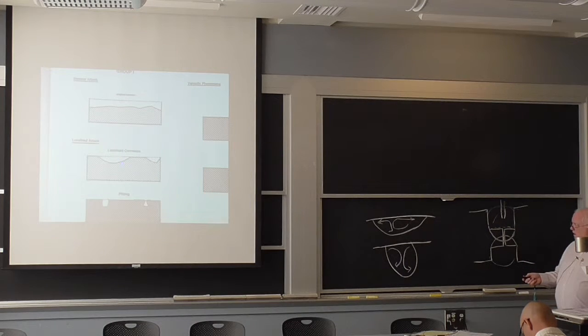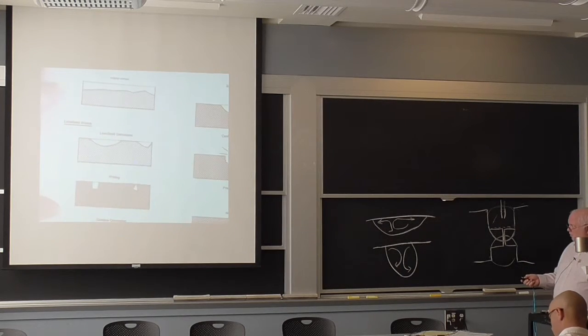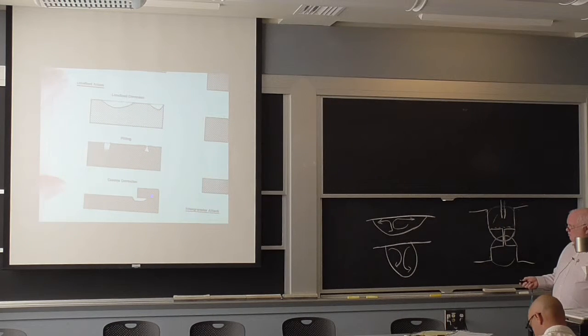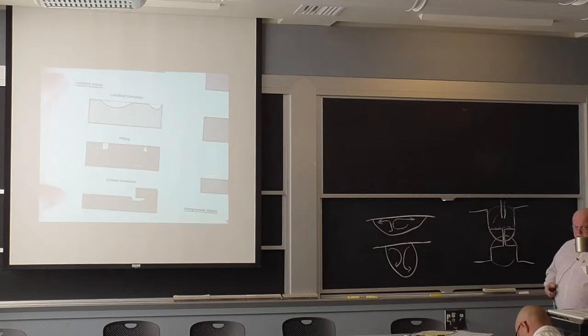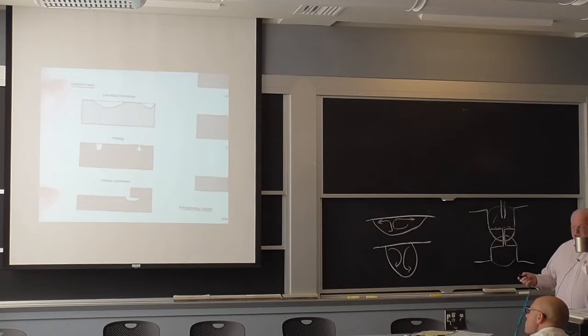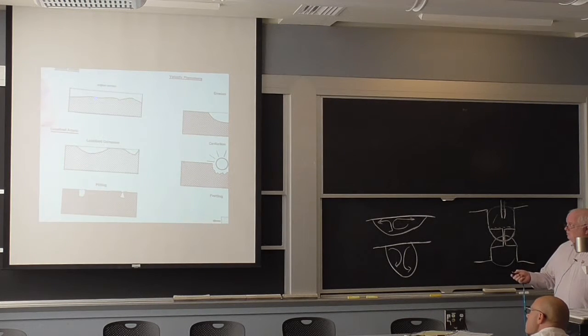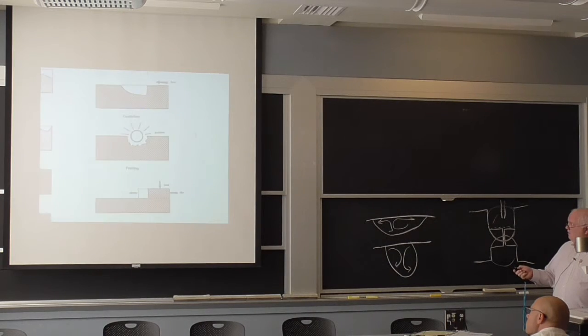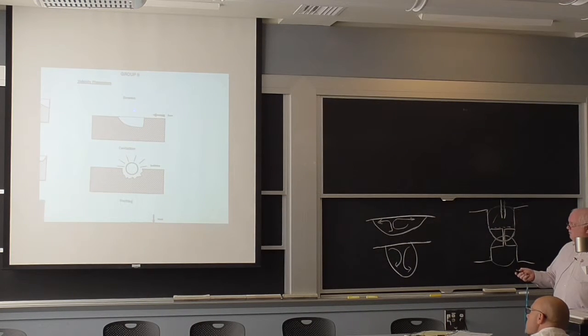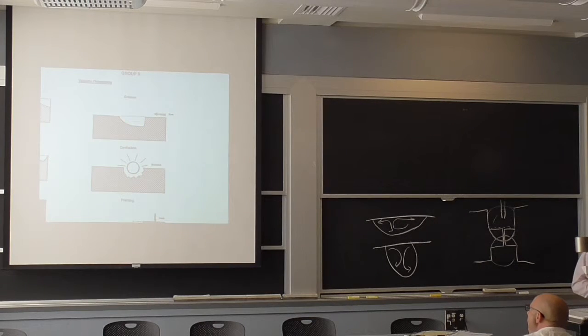You have localized attack, which is localized corrosion or pitting, or crevice corrosion. It is localized because you get a different oxygen potential inside the crevice or in the pit. For some reason, that surface oxide breaks down. Chlorides will break down the surface oxides in a lot of things. So stainless steels pit in seawater terribly, but they don't rust, generally, in seawater. You get into other things, he calls it velocity phenomena, erosion. Well, that's when you lose the chromium oxide on the surface. We talked about that.